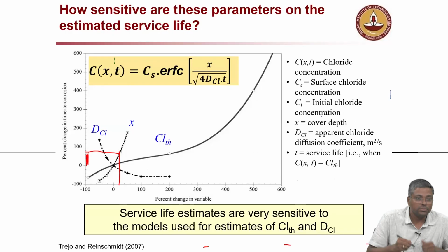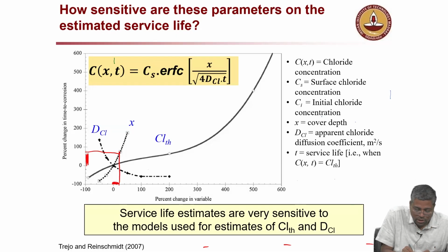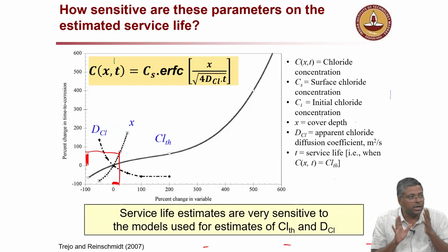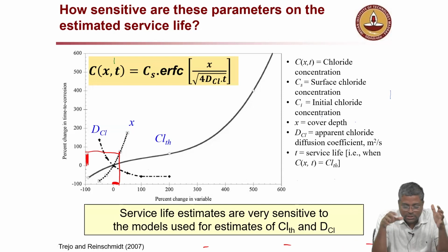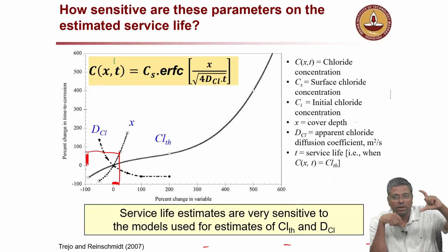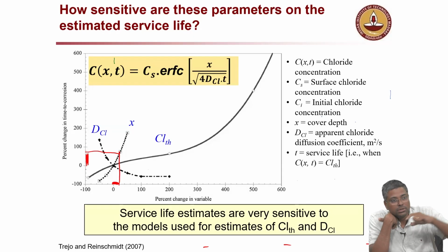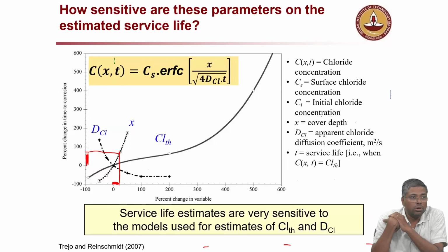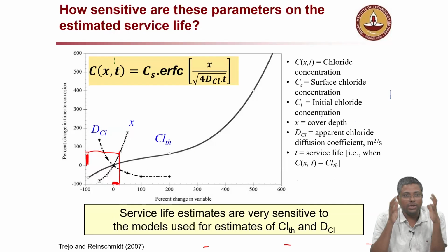This much it has changed for a very small change in X value. Is this clear? I don't want to just keep moving if it's not clear. Is it clear? A small change in the parameter is creating a big change in the time to corrosion initiation. That means the steeper the curve at 0, the more influential or more sensitive it is. So that's again telling cover depth is very critical when you want a durable life. Okay, the most critical thing is cover depth.